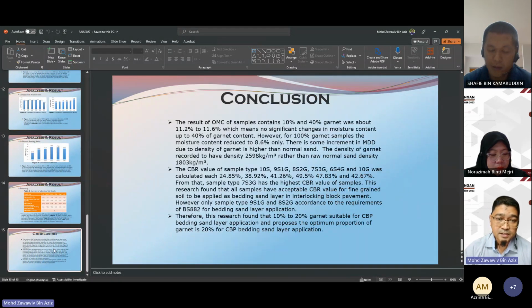So for the conclusion, the optimum moisture content of samples containing 10% and 40% garnet was about 11.2% and 11.6%, which means no significant changes in moisture content up to 40% garnet. However, for 100% garnet samples, the moisture content reduced to 8.6% only. There is some increment in dry density because the density of garnet is higher than normal sand. Garnet recorded a high density of 2598 kilograms per cubic meter, rather than normal sand density of 1803 kilograms per cubic meter.